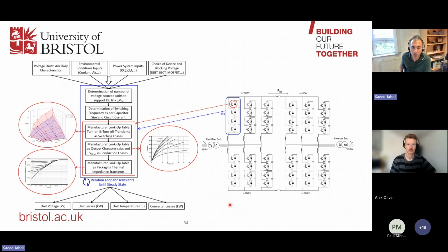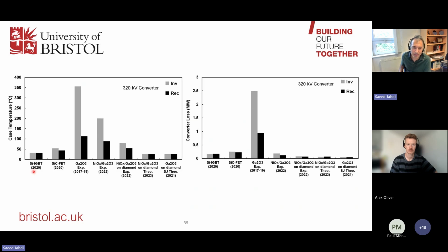So this is our methodology. We have considered the HVDC, VSC HVDC converters, and we have gone through the normal power loss calculations, for example, that you would expect. And we have seen that the earlier stage gallium oxide, in terms of, for example, the case temperature or the converter power losses, has been really bad. Compared to silicon IGBT and silicon carbide MOSFET, gallium oxide was not performing, and the power losses were too much. The case temperature was too high for reliability.